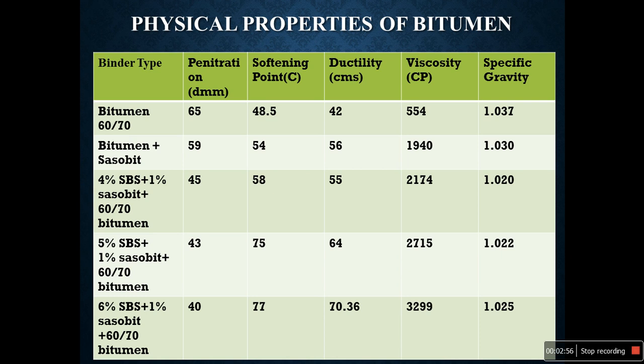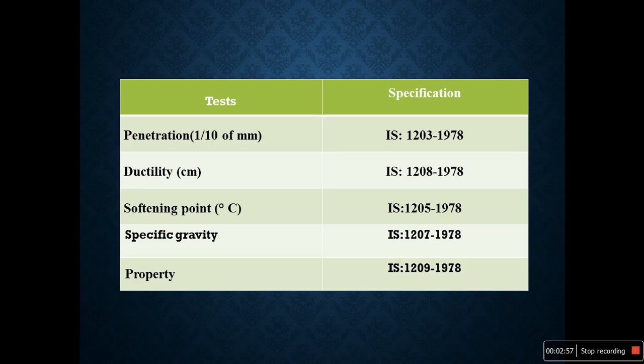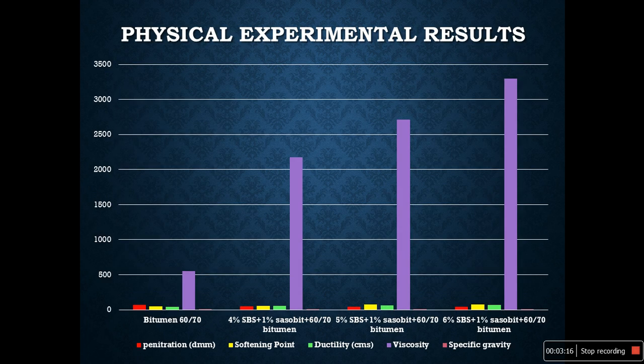The tests to be conducted are: penetration as per IS 1203, ductility as per IS 1208, softening point as per IS 1205, specific gravity as per IS 1207, and viscosity as per IS 1209. These are the physical experimental results.